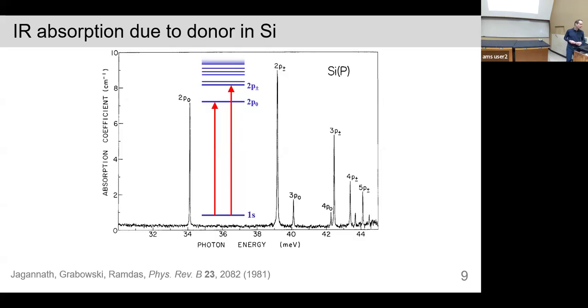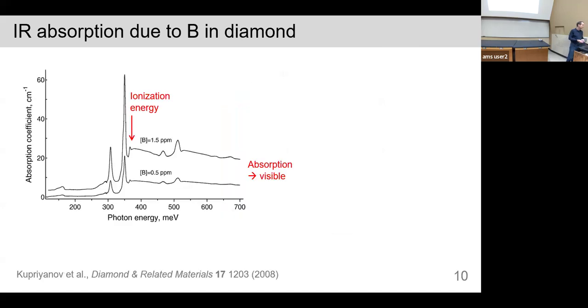So this is in the infrared. So these energies are in the tens of millielectron volts, far infrared. So if you had infrared eyes, you'd say, oh, that seems to have been doped. It looks different, but it doesn't look any different to the human eye. But there is something that you can see, and that is boron in diamond. And it acts a lot like boron in silicon.